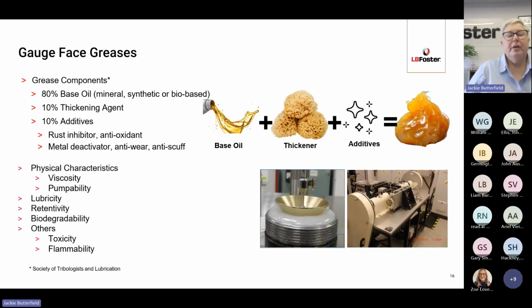The lubricant is the base oil, and that sits within the grease matrix. As the wheel rail forces interact with the grease, the oil is squeezed out of that sponge and distributed along the track. They consist of a base oil, which is roughly 80% of the grease constituents, and that can be a mineral oil, a synthetic oil, or even a bio-based oil. Into that you add thickening agents at about 10%, and also another 10% of additives.